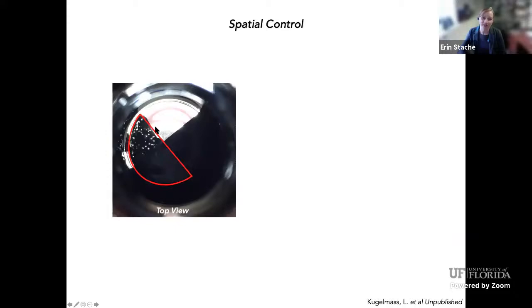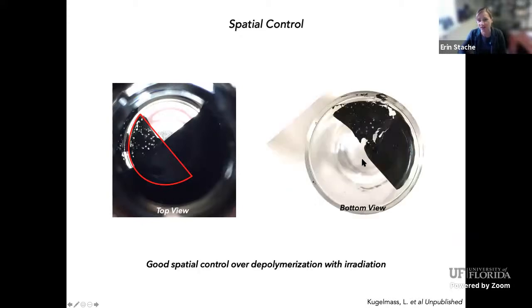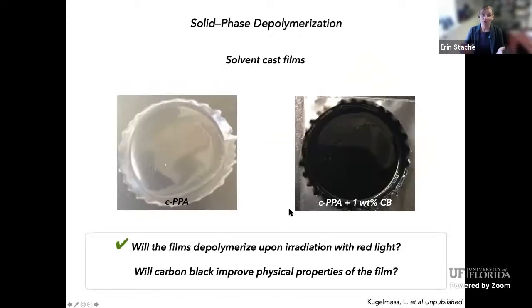And then after irradiation, you can see that the film has depolymerized. You can see that this is all spotty right here. This is still covered up. And when we uncover it, we can see that we get pretty good spatial resolution. Over the film, it's depolymerized where we're shining light, and it's intact where we are not shining light. Now, this is not the best photo mask, and this isn't collimated light or anything. So this is actually really impressive spatial resolution. And we're working on some other more complex techniques to show that we can do this, which we think we definitely can.